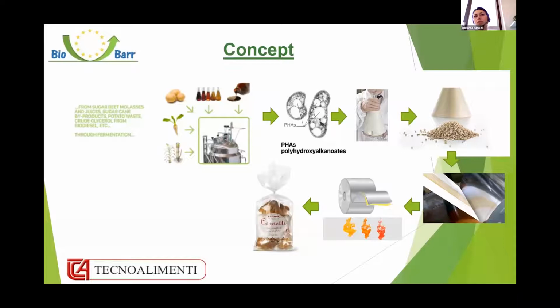So from these sources, we were able to obtain PHA, so we recovered it, we purified the PHA, and through two different phases, first the obtainment of powder, and then the compounding phase for obtaining the pellets, we arrived at the extrusion phase for obtaining these flexible films. These flexible films were functionalized with different solutions, in particular the introduction of a very thin layer of aluminum, metallization on one side, and lamination with PLA on the other side.